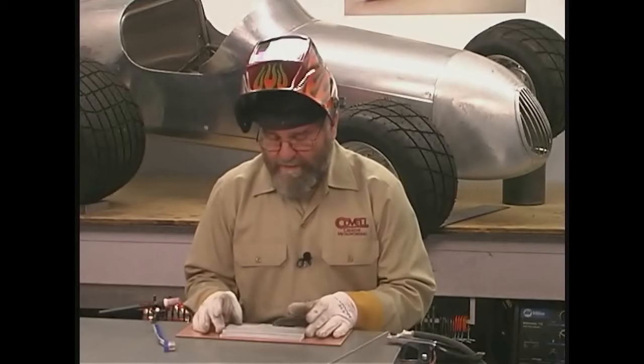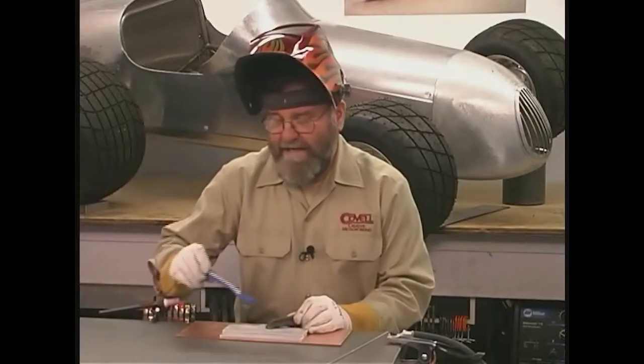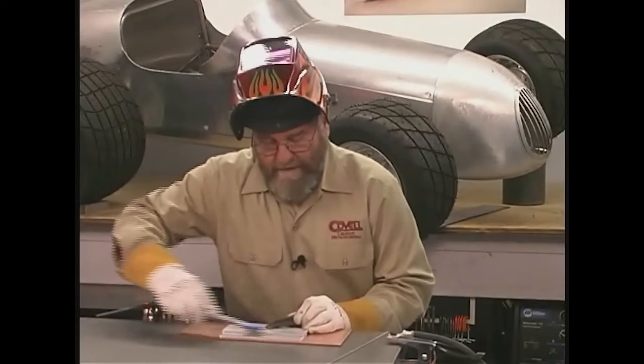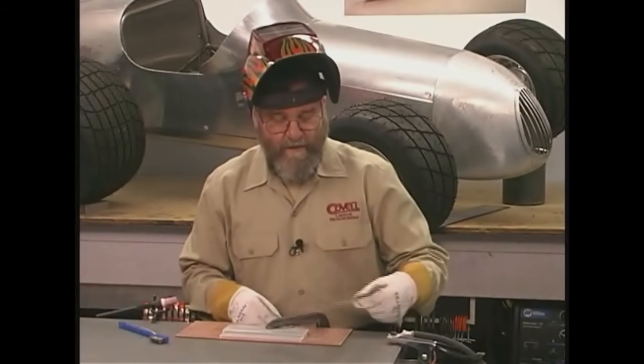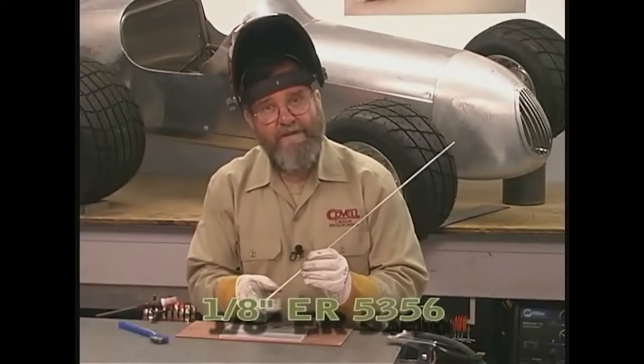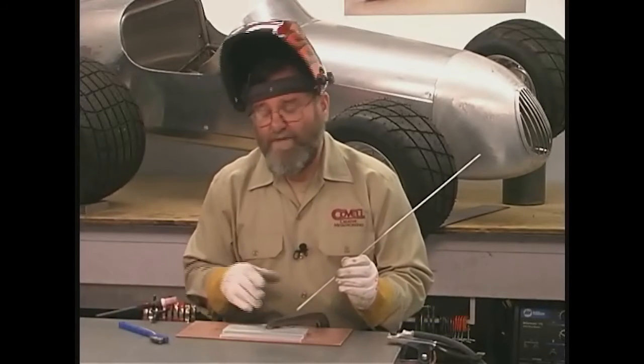For our lap joint demonstration, I'm going to be welding 3/16 inch thick 6061 T6 aluminum plate, and each piece is 2 inches wide. So I'm going to place one piece over the other. I'm going to use a small C-clamp to hold them into position. And the C-clamp does two things. It keeps them from moving as I'm doing the tack welding and finish welding. It also is going to electrically ground the parts, which is important. And I have a dedicated brush that I use for aluminum. I'm going to use that to clean the joint. And I'm going to put one tack weld on this corner and then start the weld from the other side. The welding rod I'm using is 1/8 inch diameter 5356 rod. That's the best match for the 6061 T6 base metal.